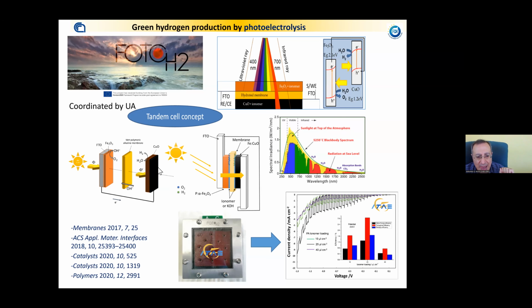This is a nice concept, the so-called tandem cell, using the AEM membrane, the anion exchange membrane, in between a photoanode and a photocathode. This is a transparent membrane. The photoanode, made of iron oxide, is absorbing the low wavelengths, the high energy part of the solar spectrum, with a 2 eV gap. The low energy, higher wavelengths, passes through the membrane with a 1.2 eV gap, reaching the photocathode. This gives a good matching with the solar spectrum, allowing conversion of most of the solar energy.